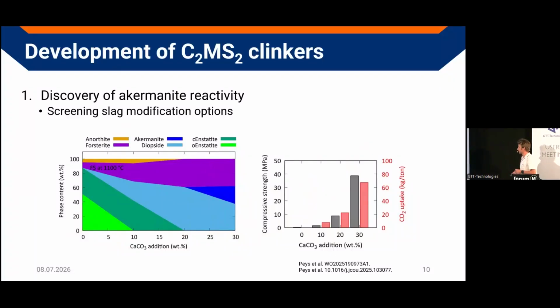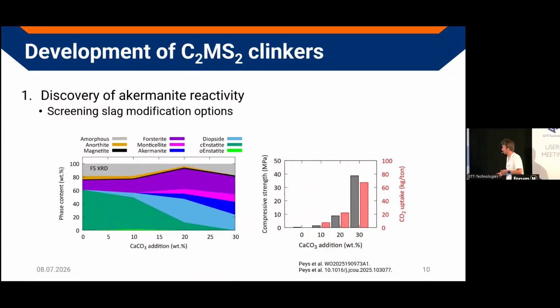And we noticed in the characterization that it was because of the presence of this akermanite. These are the XRD results of the real ones. So you can see, well, the simulations worked quite well for the system. And we actually noticed also by characterization of the materials after carbonation, it's the akermanite that completely reacts and gives the strength to our material. So this was the first point. We discovered that the akermanite was very reactive.